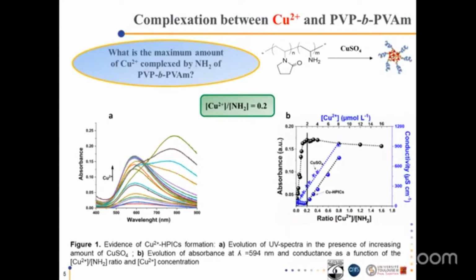To understand the peculiarities of HPIC formation, an increasing amount of copper sulfate was added to a constant amount of block copolymer, so that the molar ratio between copper ions and amine groups of the polyvinylamine block changed from 0 to 0.2. Obtained compositions were examined by UV spectroscopy and conductometry. The formation of the complex was confirmed by the presence of a band with lambda maximum 594 nanometers, figure 1a. Above a given concentration of copper sulfate, a new band was observed at about 800 nanometers, which means the appearance of free copper ions.